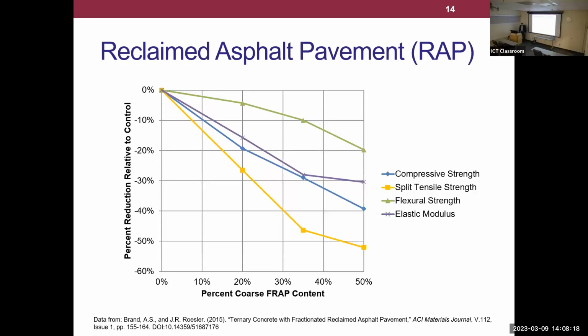This is work from years ago that I did. This is increasing RAP content. We did fractionated RAP, which we also called FRAP, so you'll see FRAP and RAP on here. Basically, we replaced up to 50% of the coarse aggregate in a concrete with RAP. You can see the significant reductions; we're dropping almost 50% on tensile strength. It's a fairly significant drop. Traditionally we would have to over design our pavement to accommodate for that, but that was a different study. That's a different story. You actually don't have to, but I'm not going to talk about that today.